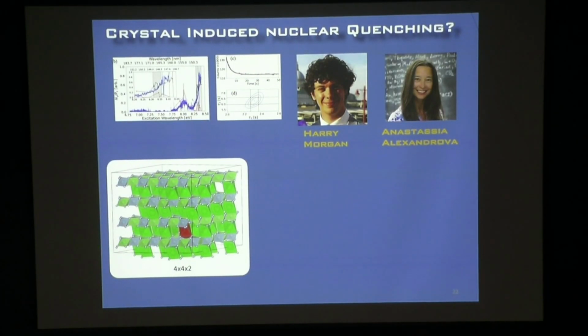You have to do these big unit cells because of the way the boundary conditions in these DFT calculations work. If you just tried to do the unit cell with one thorium in it, you would just have a thorium everywhere, the way the calculation runs with periodic boundary conditions. And so this is about as big as you can go with the supercomputers that we have access to. There's like 2,000 electrons here. It's a crazy calculation. And what they calculated are shown here.